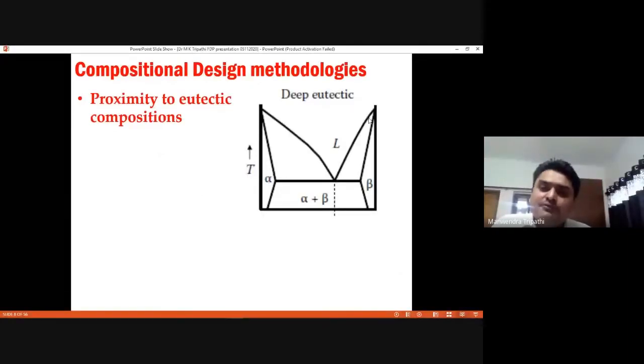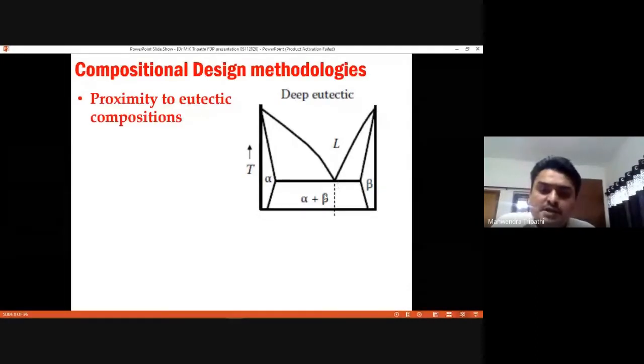So the very first approach was proximity to eutectic composition. This is a binary system. Here you are putting composition and temperature, and this kind of phase diagram we call the eutectic phase diagram. So normally it is noted that for the very first alloy which was made, the gold silicon alloy, the composition taken was the eutectic composition. There is a specialty of the eutectic composition, that the liquid remains stable down to the lowest temperature, right? So it was noted that if you quench it, then normally it is converted into glass. It does not crystallize, because at the eutectic composition, 2 phases have to separate, alpha and beta. And when you cool it very fast, there is no sufficient time and temperature for this alpha and beta separation to take place. And once it cannot take place, it solidifies as metallic glass.